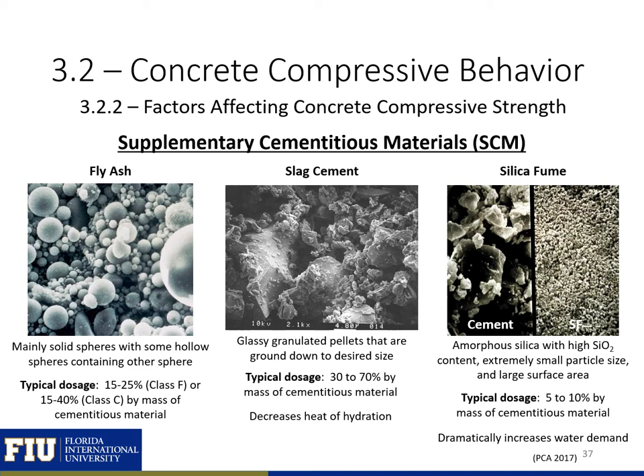Silica fume is an amorphous silica with high SiO2 content. Silica fume has an extremely small particle size and a large surface area. This results in a dramatically increased water demand. The typical dosage is 5 to 10% by mass of cementitious material for silica fume.